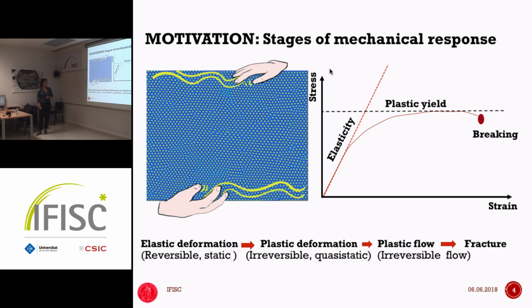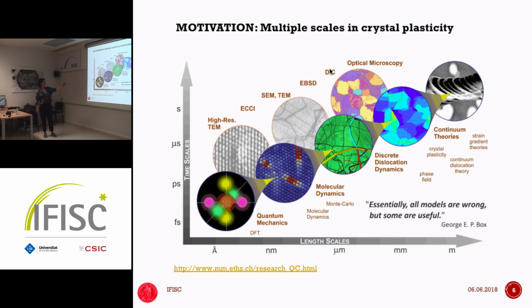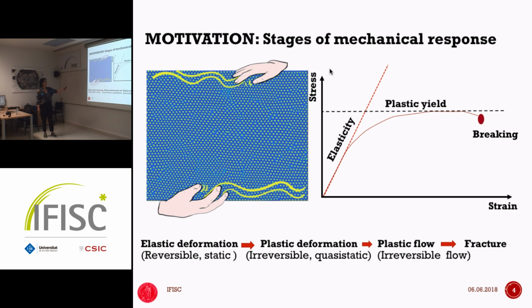Okay, that's one motivation. In particular, when we are looking at the mechanical properties for these crystalline materials, but in general for all materials, there seem to be different stages of deformation. So if you would plot the deformation, this vertical axis corresponds to the force per unit area, the stress, and this is the response measured in terms of the strain, the relative deformation. You would have the regime of linear elasticity for very small applied forces. You have this linear response, the elastic spring, right? But as you increase the applied stress, you enter into this nonlinear regime, which is also called the plasticity regime. It's dissipative, it's irreversible, unlike the elasticity regime, and eventually it leads to breaking of the material, failure.